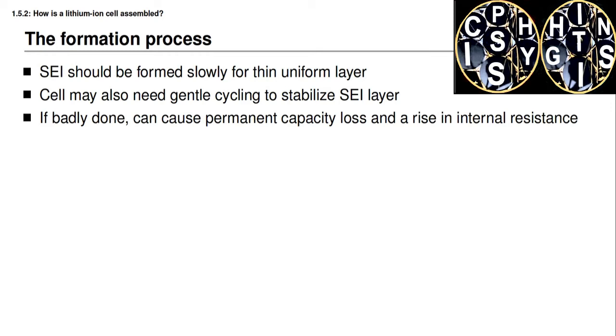If the formation process is badly done, then this SEI layer will be thick and non-uniform, and it may be brittle, and it may easily break down as the battery cell is being operated in the consumer application. Anytime the SEI layer breaks down, it exposes more graphite to the solvent, and at that point the solvent will react to the graphite and form additional SEI products, which will reduce capacity and increase resistance. So while the SEI layer is formed for the first time when we charge the battery cell for the first time, it actually does tend to grow somewhat over time due to failure of the existing SEI layer and building of additional SEI layer.